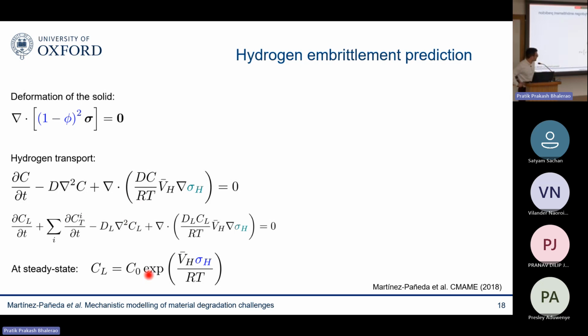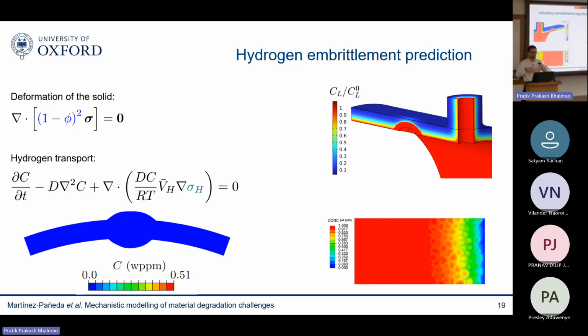You can see that the steady state solution is something like this, where you have an exponential term with the hydrostatic stress inside of that exponential term. So the hydrogen concentration is going to be very, very large near cracks and other stress concentrators. But then when you implement this into finite elements, you get behavior like this. These are just some representative results. Here you see a pipeline where we're increasing the pressure of hydrogen on the inside, and you see how the hydrogen distributes. This is another pipeline with various defects and components, and this is within the microstructure. So whenever you implement this coupled deformation diffusion model, which is relatively straightforward to do, even in commercial finite element packages, then you can predict the distribution of hydrogen within your component and within your microstructure.